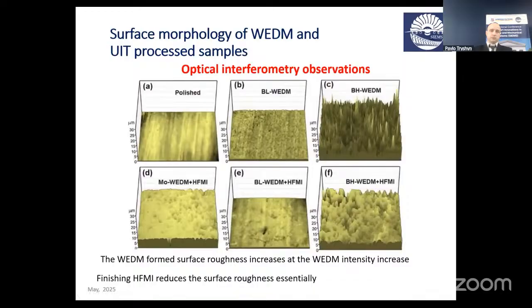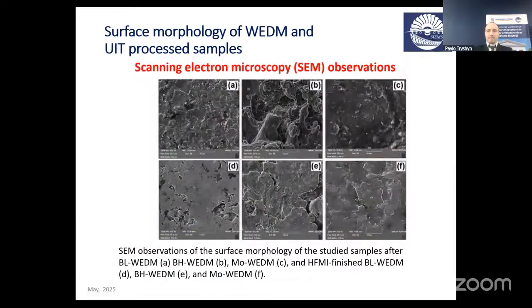It is important because we avoid stress concentration on the surface relief and thus can prolong the operation life of the material. This conclusion was confirmed by scanning electron microscopy observations. On this slide, you see the morphology of the surface after the light EDM process, middle and hard EDM process. The highest roughness is observed after the hard EDM process. Fortunately, surface roughness and morphology are much smoother after finishing using ultrasonic equipment.